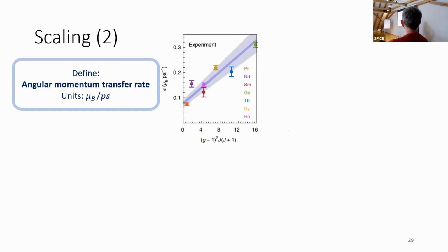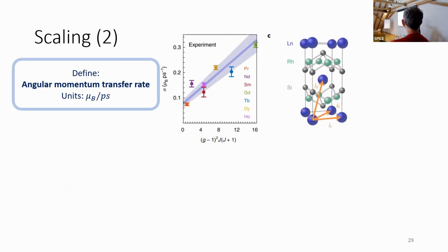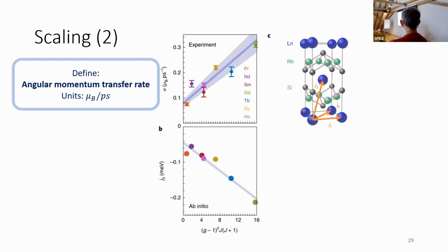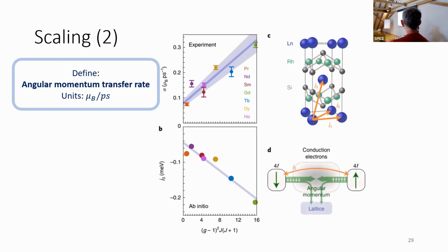Some of my colleagues were less. So to be clear, if this is our unit cell, this is one layer. This is another layer. I'm talking about this coupling. So our theory colleagues calculated this and found that it also scales with the de Gennes factor, while these guys, which I'm not showing you because I'm lazy, do not scale with the de Gennes factor at all. Also, all the other couplings in the system, they calculated many more. And so the last thing I'm going to point out is that this does not go to zero. This does not go to zero at all.